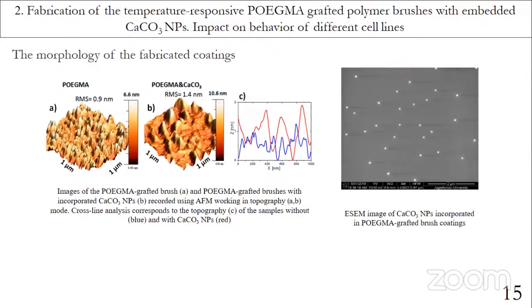It is well known that calcium carbonate nanoparticles during synthesis form a mixture of vaterite and calcite forms, and the ratio between these forms depends on the conditions of the synthesis. In addition, the vaterite usually transforms to calcite, which is a more stable calcium carbonate polymorphic form, represented by cubic crystals and depicted in this photo.